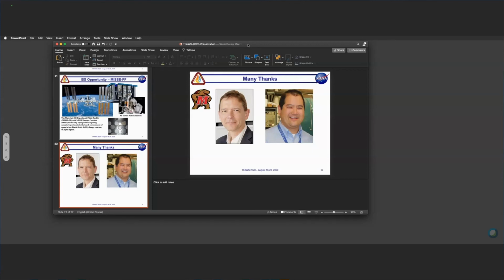Okay, we've got a question here. How well can you verify that you have coverage of the ITO on the surface? Right, so one way that we can verify that we have good coverage is to go through our SEM process, where we can actually visualize what is going on with the pigments themselves. The other way would be through the coating process. We bind the coated pigment with our binder, go through a spray process, and then we can go through a very simple 4-point probe measurement across multiple regions within our substrate to verify that we actually have a conformal coating and a good coating across our surface.